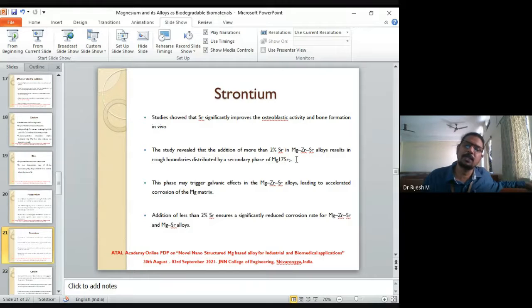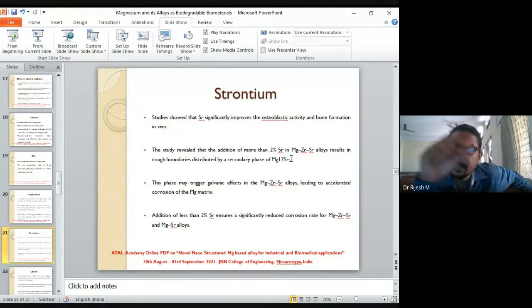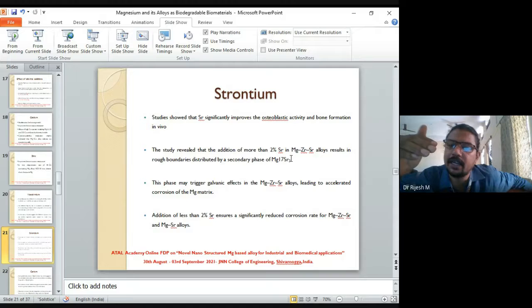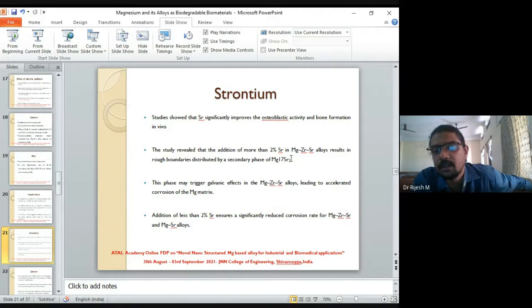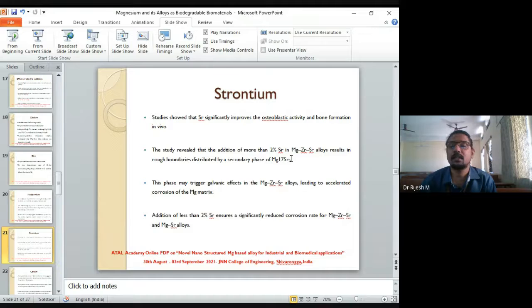Mg17Sr2 is an intermetallic precipitate formed out of adding strontium. They are formed over the second phase. Now what happens when you have some precipitate over the grain boundaries? It becomes anodic compared to grains. This magnesium, which was supposed to be there inside the grain, Mg17 is present on the grain boundary. So the grain boundary becomes more anodic than the grain. So you have a galvanic effect, and the corrosion is aggravated in that case.